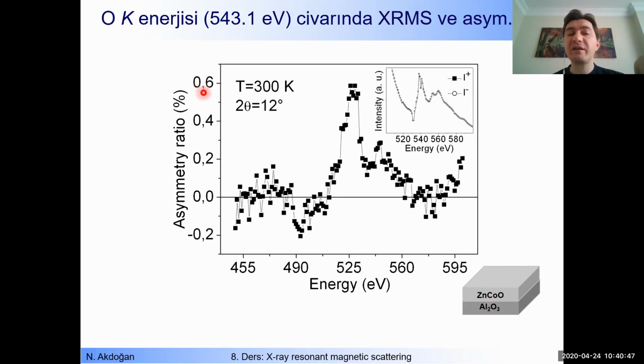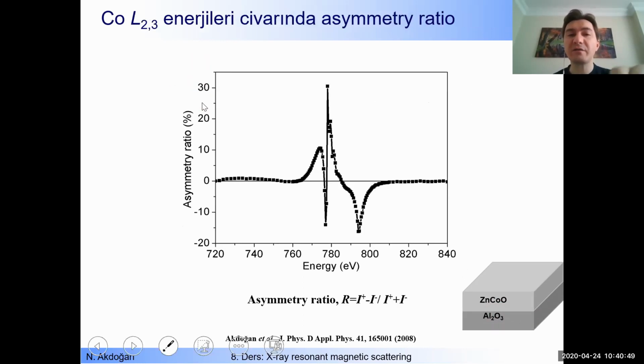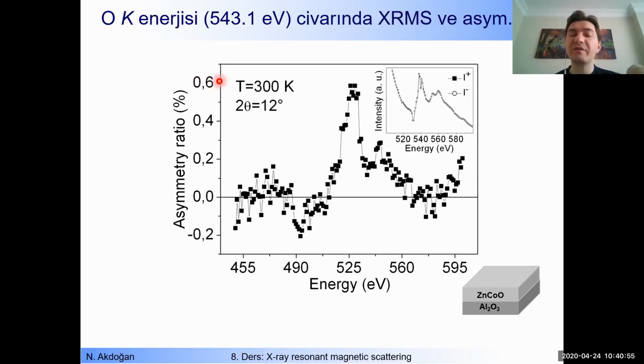Of course, it is very small compared to the magnetic signal from the cobalt. Here we have 30%, here we have 0.6%, less than 1%, but it is a real signal. It is not noise. We have many data points here. So what is the meaning of that?